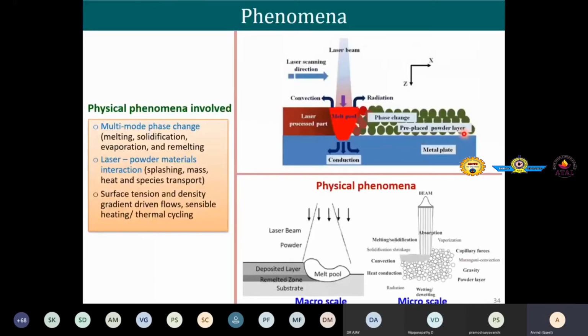You see here the schematic. Locally, we have the melt pool. The right side is the remaining powder in the current layer. The left side is the solidified part, and the laser is scanning from left to right. In the melt pool, you have several thermal and fluid phenomena: flow of molten metal, convective heat transfer, conductive heat transfer. Some of the metal is also getting vaporized, which is evaporation phase change. Then this molten pool is solidifying, so from liquid to solid phase change. Before that, powder material is becoming liquid, so powder to liquid phase transition.